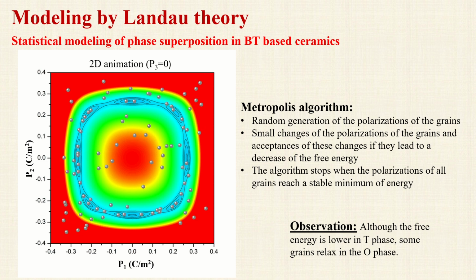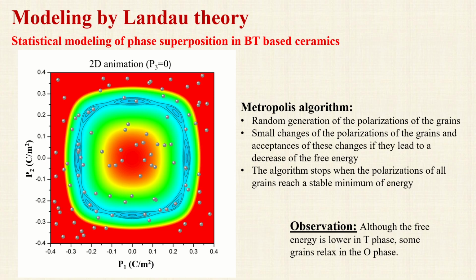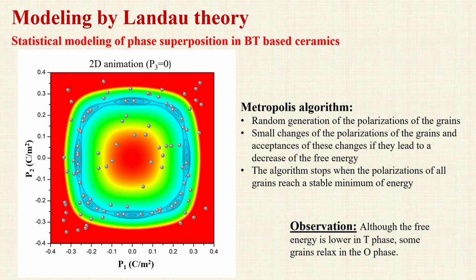In order to derive some quantitative information about the concentration of the phases at different temperatures and compositions, we employ the simple Monte Carlo algorithm. The algorithm consists of successive and small modifications of the polarization of the grains until a stable minimum of energy is reached. The procedure starts from a random configuration of the polarization of the grains.